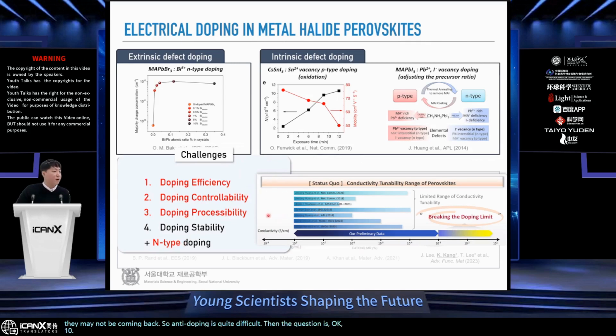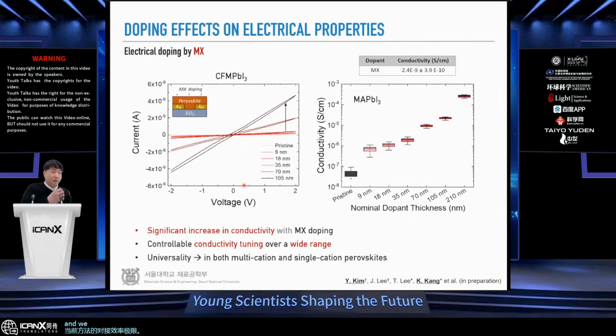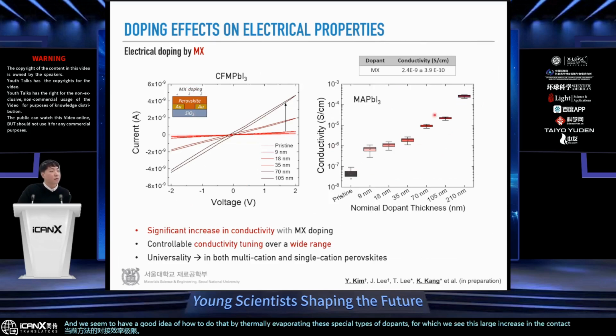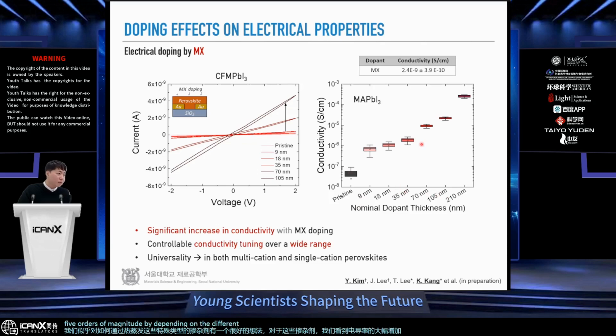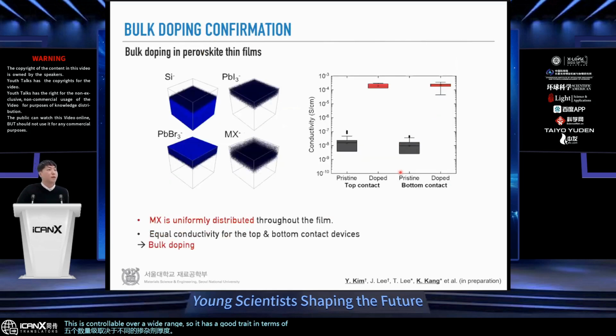Then the question is, okay, how can we break the limits for the doping by inducing N-type as well as breaking the doping efficiency limit for the current method? And we seem to have a good idea of how to do that by thermally evaporating these special types of dopants, for which we see this large increase in the conductivity up to 5 orders of magnitude, depending on the different dopant thickness. And this is controllable over a wide range, so it has a good trait in terms of controllability. And we see that this is bulk doping by ToF-SIMS as well as doing the top contact and bottom contact. So what we're hoping to do is continue by preparing this paper to understand the mechanism, which is not so clear, as well as use it for device applications.